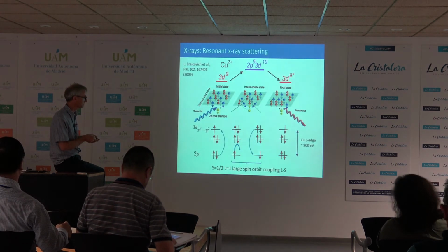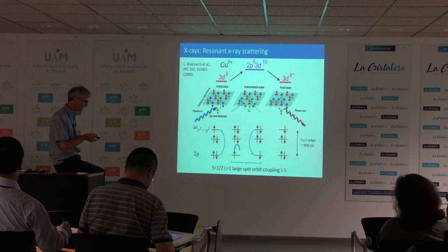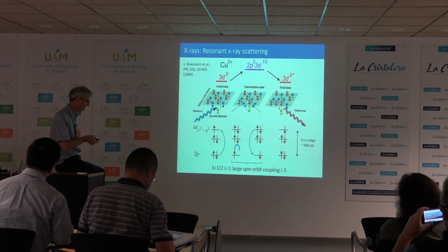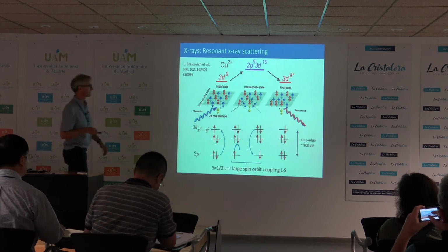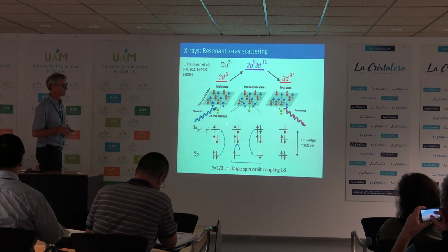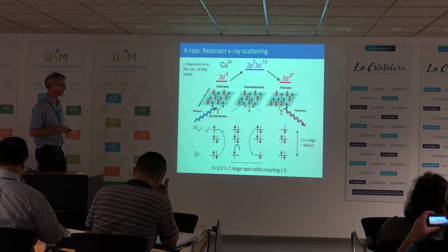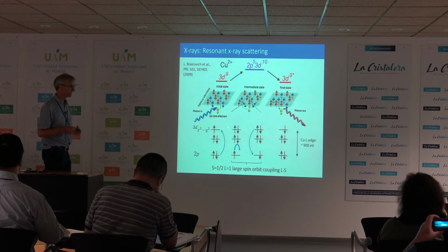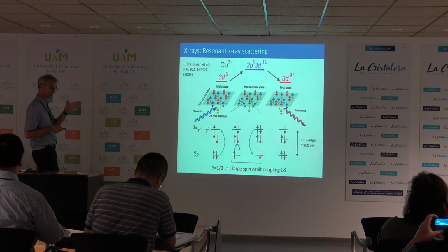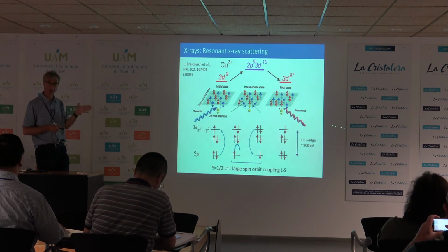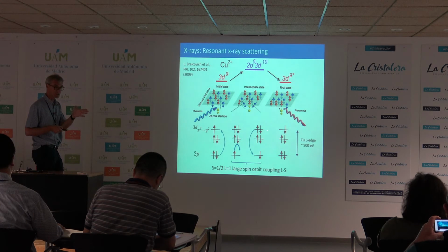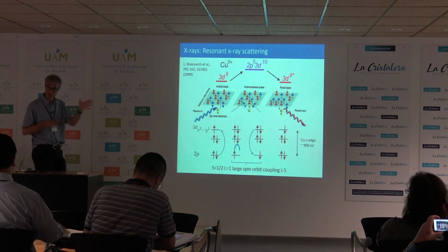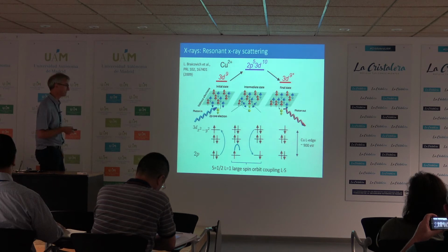Okay, so Bernhard mentioned the magnetic X-ray technique. This is a technique that's come along in recent years, primarily because the resolution of the instruments has become very good. So we now have resolutions of about 40 millielectronvolts. In fact, the neutron scattering data I showed you at the highest energies has the same resolution now as the X-rays. Of course, with neutron scattering you can improve the energy resolution vastly by just making the energy of the neutron smaller. But when you go for high energy neutron scattering, you're stuck with very high energy neutrons, and the resolution is similar to what you have with RIXS.